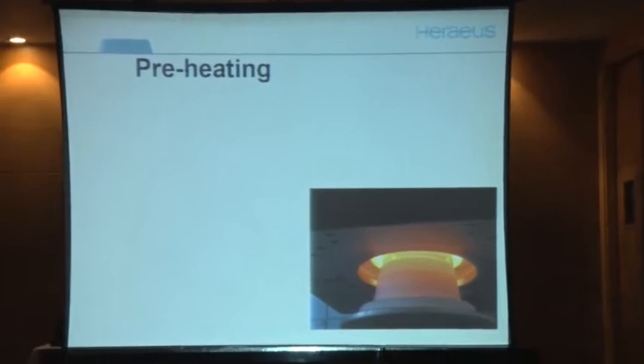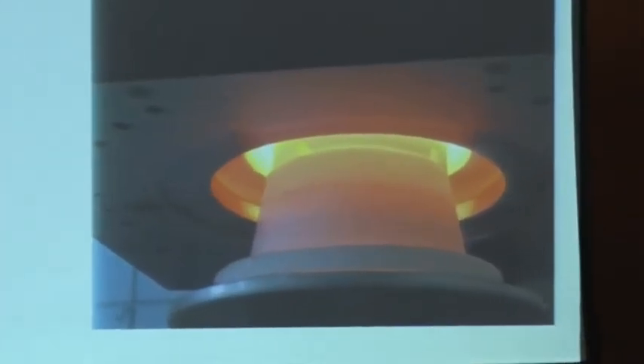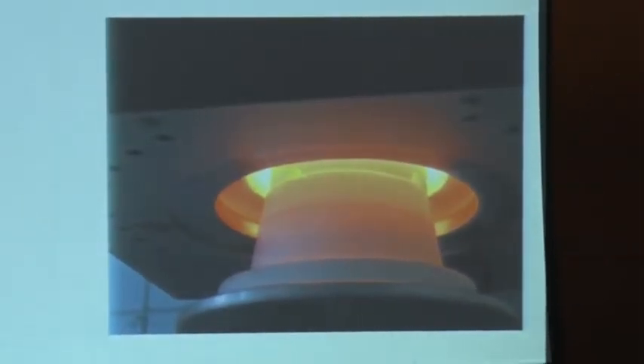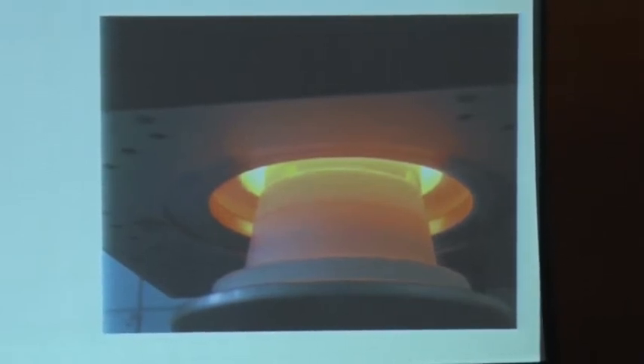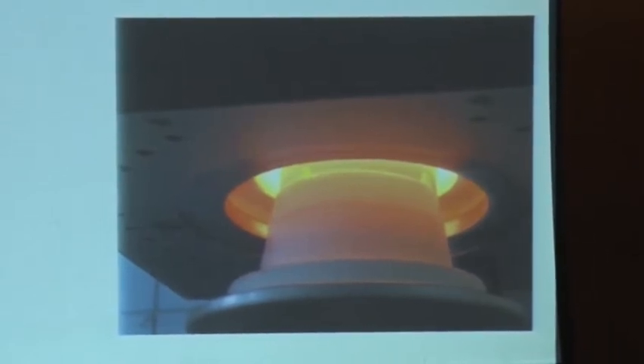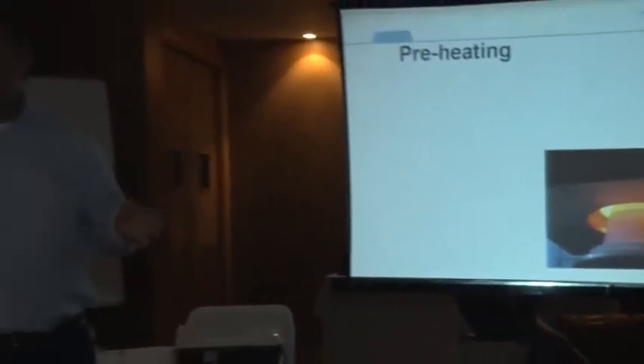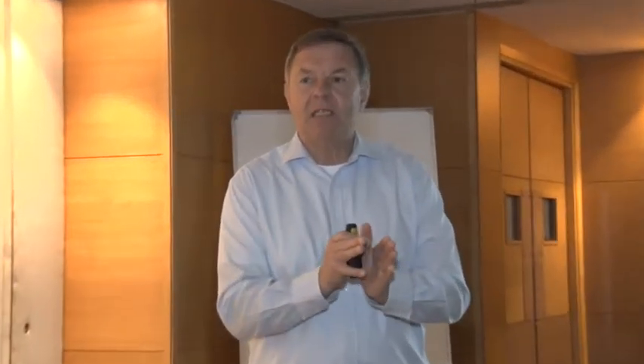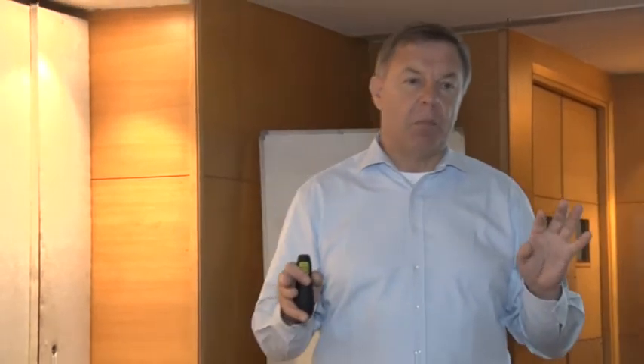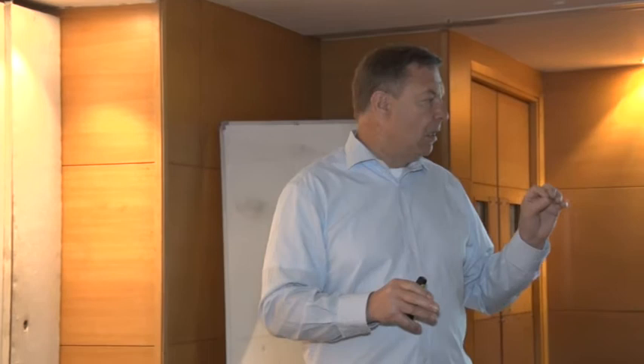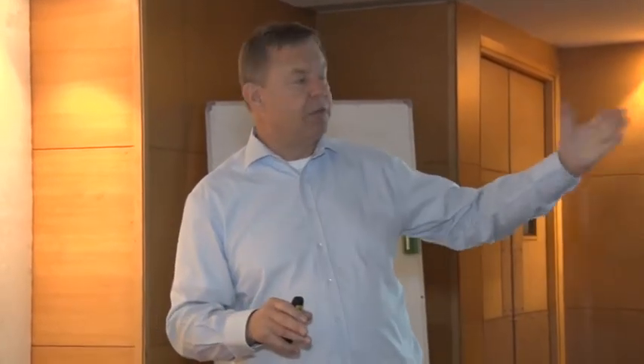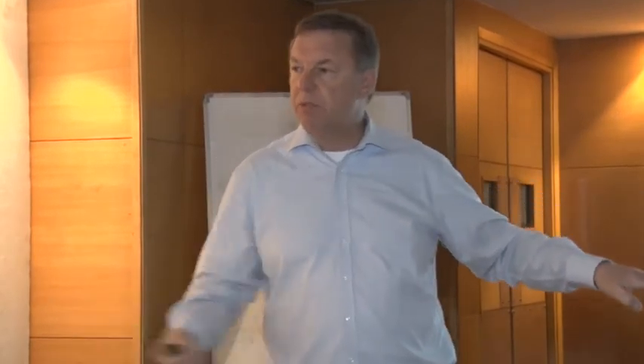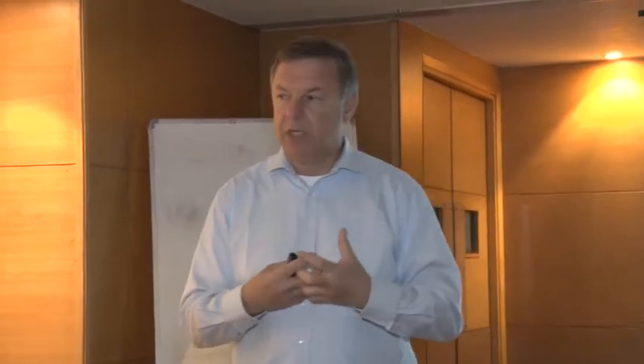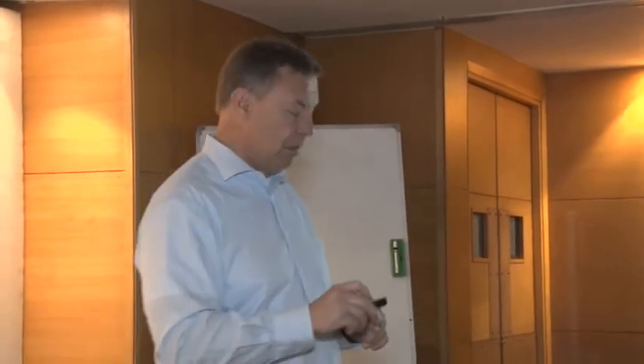A little bit, yes, because if you have a very highly viscous material, the space between the particles is a bit bigger, and then it can shrink a little more. But normally all liquids have to evaporate. Especially pre-mixed materials like paste opaque have to be produced with a special kind of glycerin. That takes more time to evaporate than normal water. That's why, if you have problems with bubbles, extend the preheating time. All the liquids start boiling at around 100, 120 degrees, and if you put the pre-mixed material in a very hot furnace, let's say after a firing the furnace is coming down, it's still 600, 700 degrees, then it starts boiling on the surface and you get bubbles. So pre-drying is very important, for the wetting, for the connection between opaque and metal or zirconia.